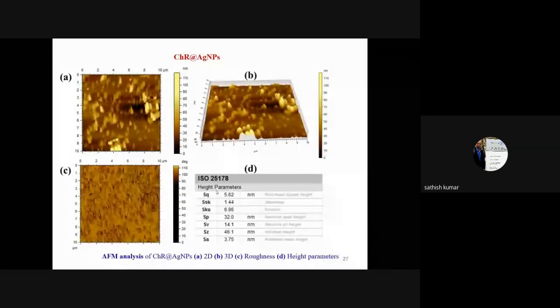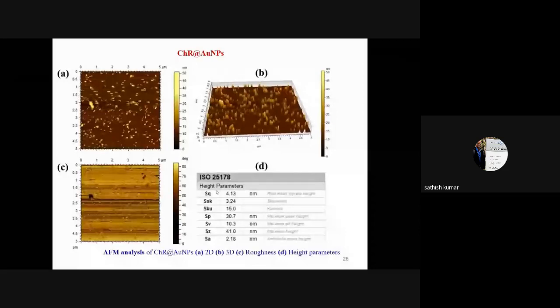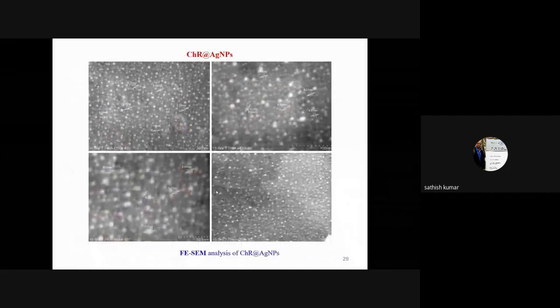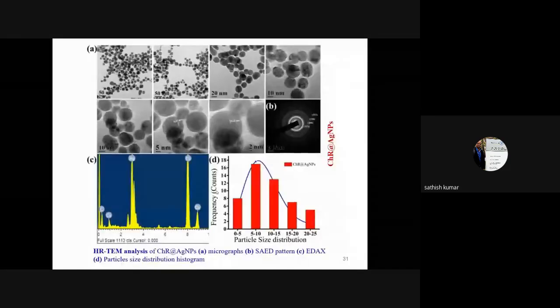The size and the topography of the nanoparticle were further analyzed with the AFM analysis. Both AFM and SEM analysis are the preliminary screening of the size of nanoparticles. But the high resolution transmission electron microscope will give the exact size range of the nanoparticle. So for this analysis, we will coat the nanoparticle on the copper grid, and then we'll perform the TEM analysis.